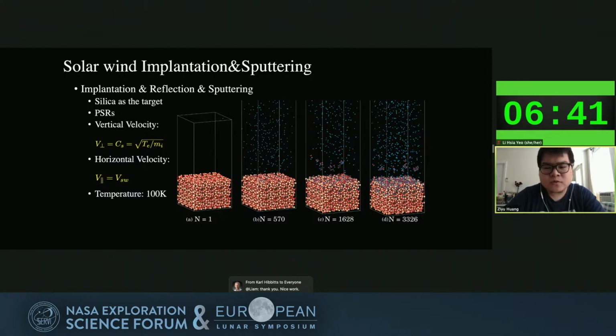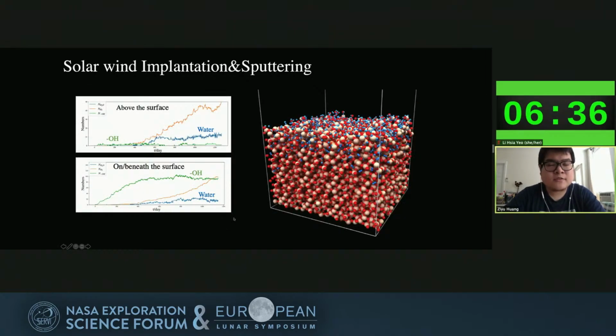And there are even some water molecules that are sputtered from the surface being injected. And then we use group analysis to identify each molecule and chemical group. The left two figures are the number of hydroxyl groups, hydrogen molecules, and also water molecules. The upper one is above the surface, and the other one is beneath the surface. The data shows that most of the hydrogen atoms from solar wind are turning to hydroxyl groups and also hydrogen molecules, H2. Water molecules are also detected, but there are very few of them.